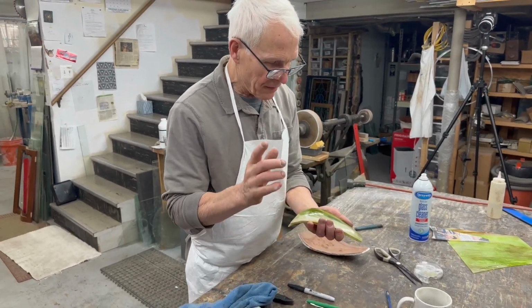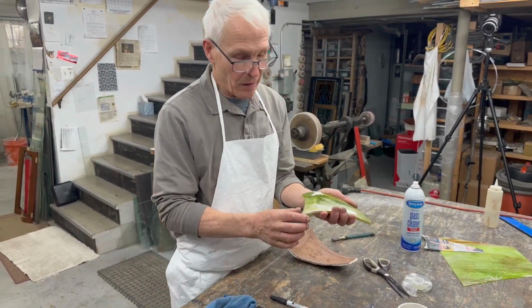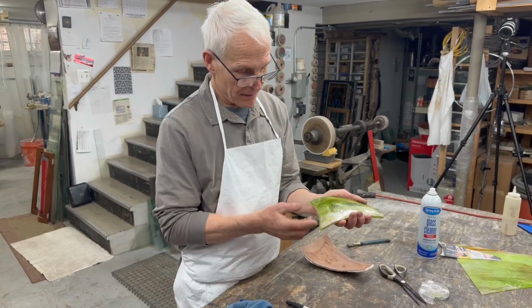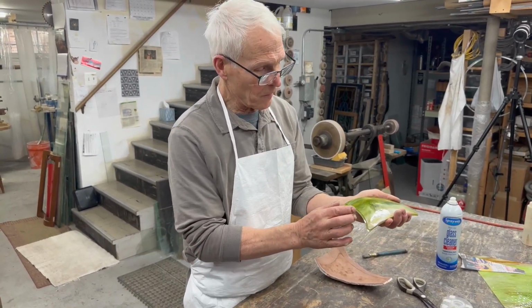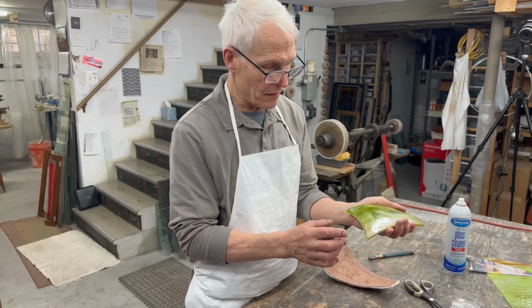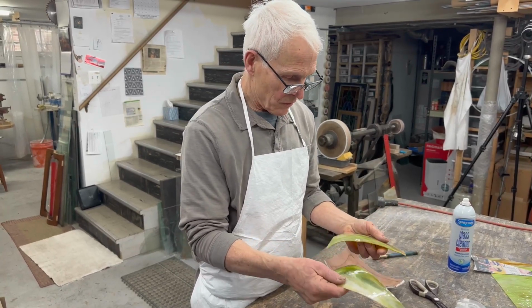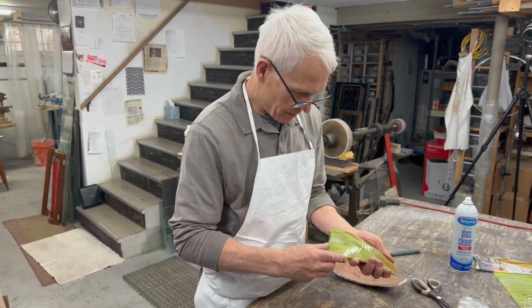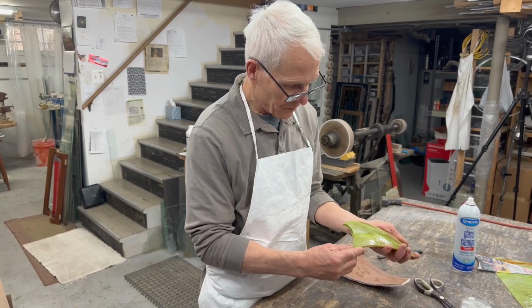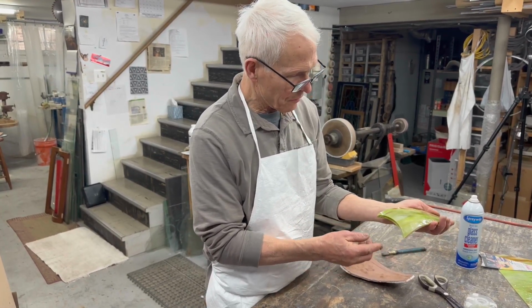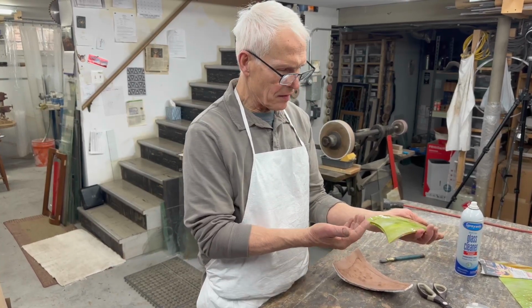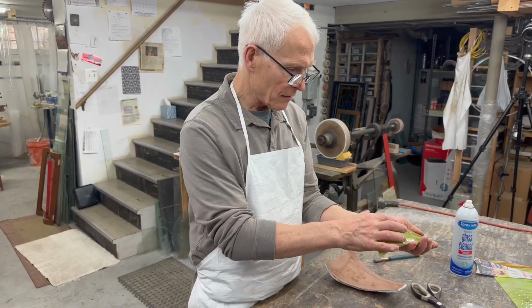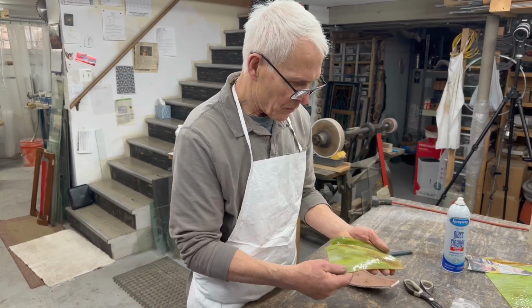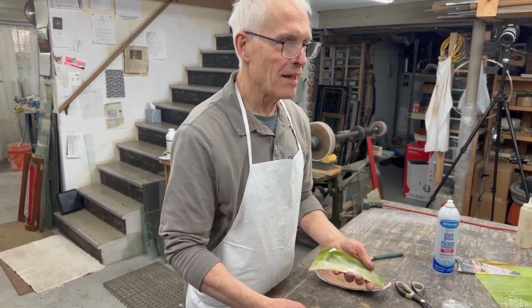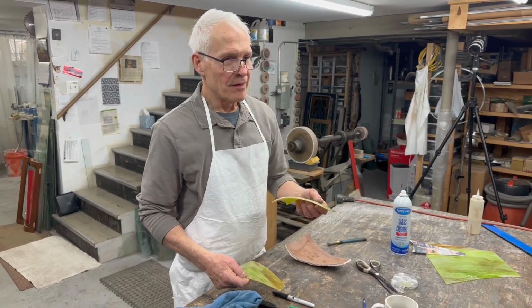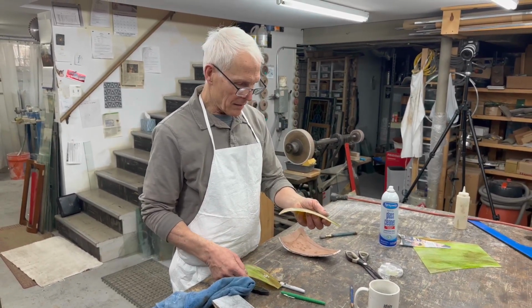Now, if you're sizing these panels, the underneath side will appear as if it's 1/8 of an inch longer. And if you switch them all out, pretty much, it's going to be pretty close. The bottom one's going to be 1/8 of an inch further along than the top one. So don't make the mistake of putting the new panel on and